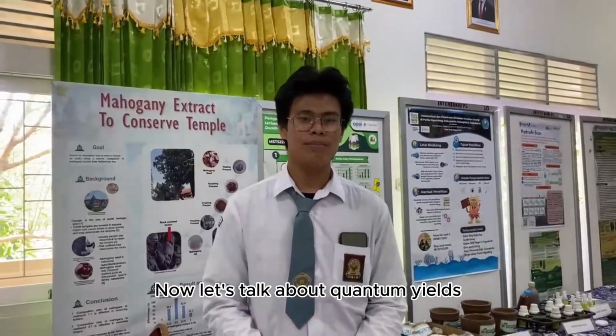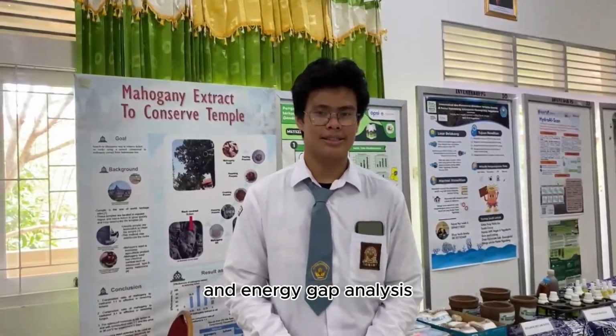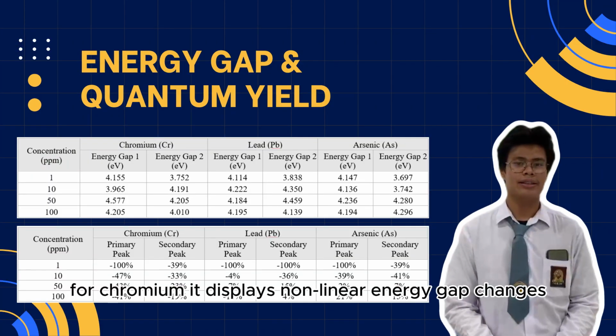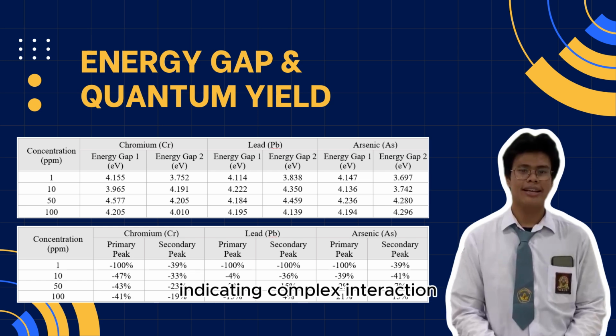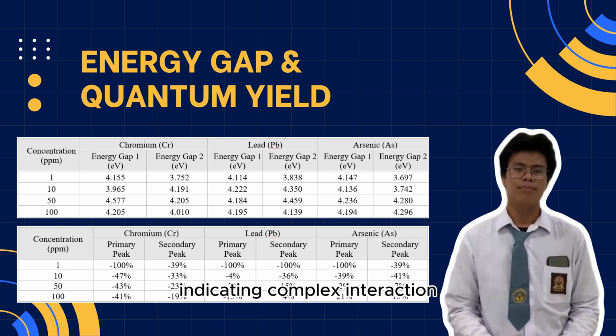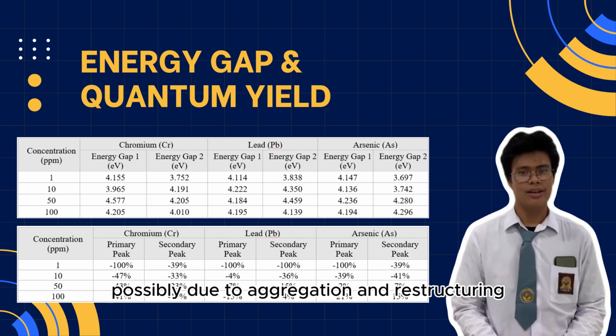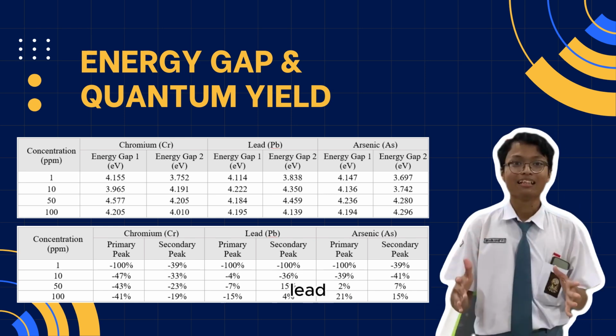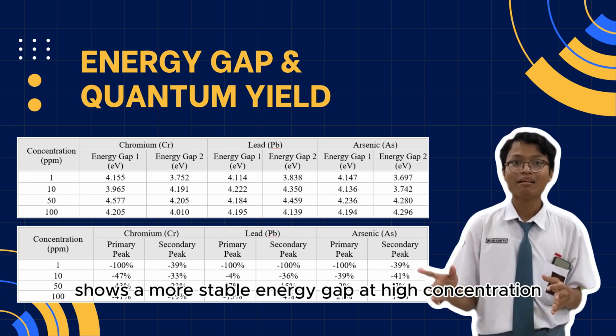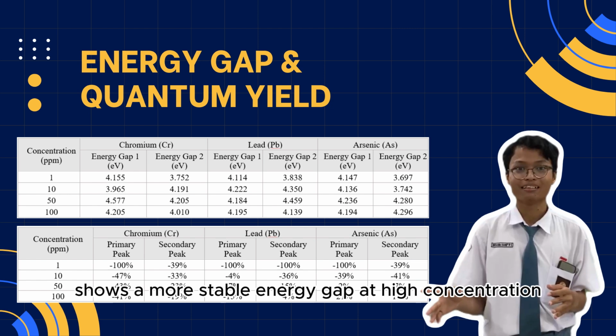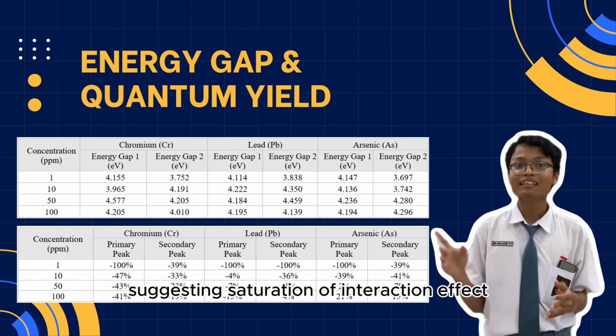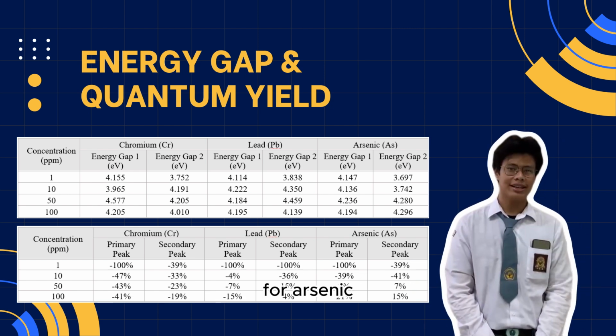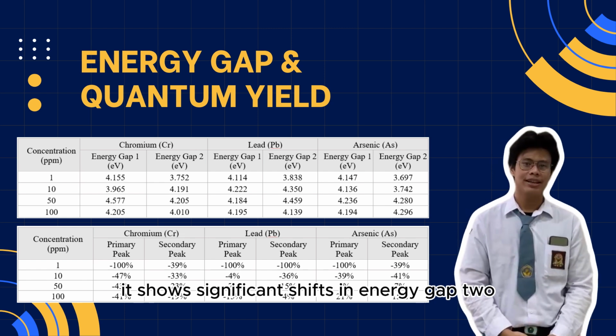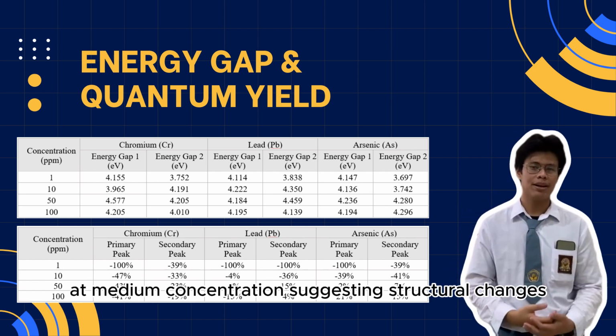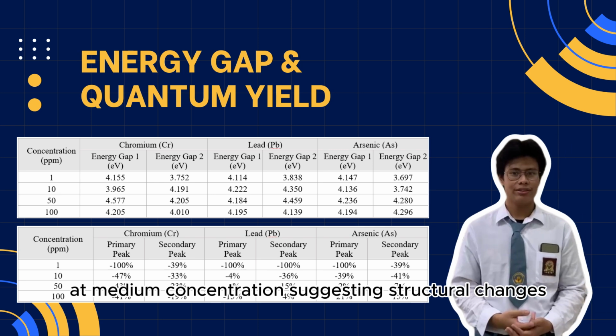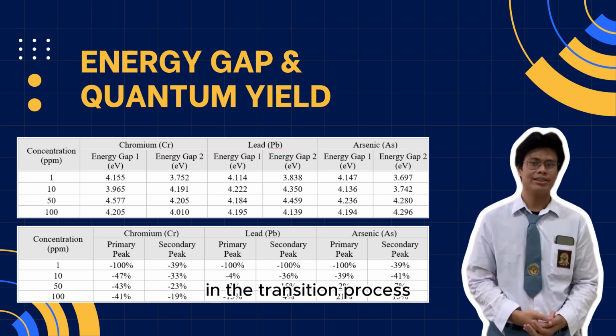Now let's talk about quantum yields and energy gap analysis. For chromium, it displays nonlinear energy gap changes, indicating complex interaction, possibly due to aggregation and restructuring. Lead shows a more stable energy gap at high concentration, suggesting saturation of interaction effect. For arsenic, it shows significant shifts in energy gap 2 at medium concentration, suggesting structural changes in the transition process.